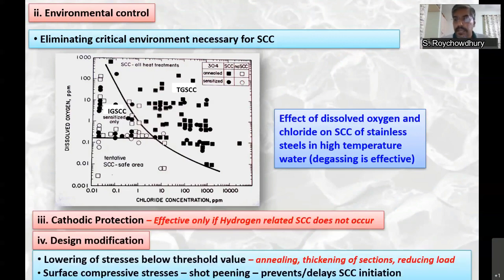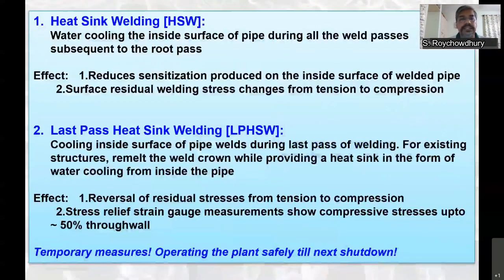Cathodic protection can help. As I told, during cathodic protection, hydrogen is evolved, and hydrogen related SCC is one of the mechanisms. So hydrogen aids in SCC growth. If that is the mechanism operative, then cathodic protection will not help. Design modification can lower the stresses. If the stresses are low, crack growth rate will be low. Tensile stresses are needed for SCC to initiate and grow. So instead of tensile, you can introduce surface compressive stresses. That can be done by shot peening. Very high hardness balls, shots, are impinged repeatedly onto the surface, which introduces compressive stresses onto the surface, and that will prevent your SCC initiation.